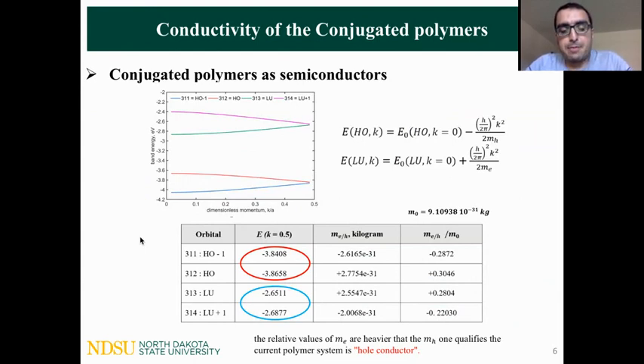Also, for this plot, if we have a momentum dispersion for frontier orbitals, we can extract some important information. For instance, if we fit a parabolic function to each curve and use the top right formula, one can easily measure the effective mass near k=0, as highlighted in blue and red circles. Also, in the right column of the figure, ME and MH, the mass of electron and mass of holes, are measured, and the relative values of ME are heavier than MH. So one can conclude that the current polymer system is a hole conductor. Next, please.